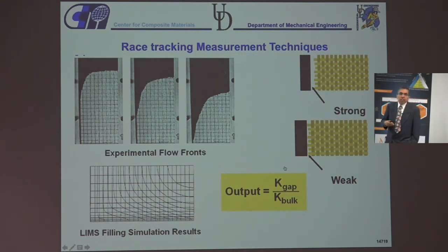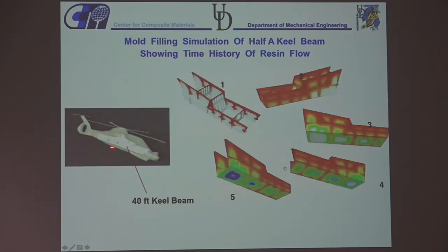So it's practically impossible to have no race tracking along the edges when you cut a fabric, because even if you cut it really well, the resistance here is going to be different than the resistance here. So there's always going to be a higher permeability in the gap than in the bulk region. And you can see this.